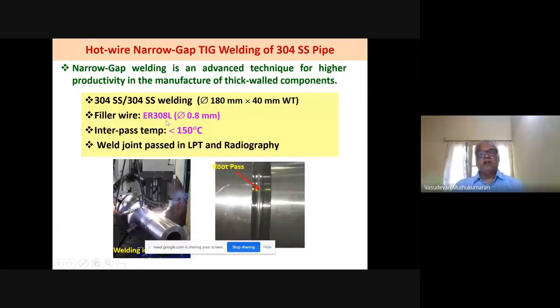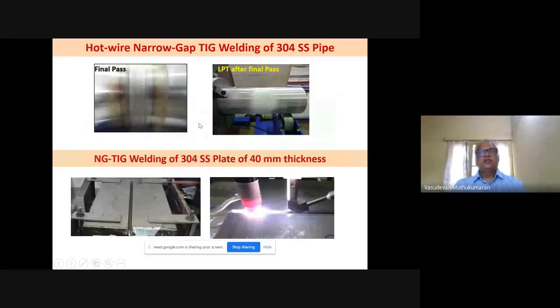Using a 308 filler wire, we maintain inter-pass temperature of 140 to 150 degrees centigrade. You can see the root pass done. We have completed the welding. You can see the final pass also here, after completing this pass with liquid penetrant testing.